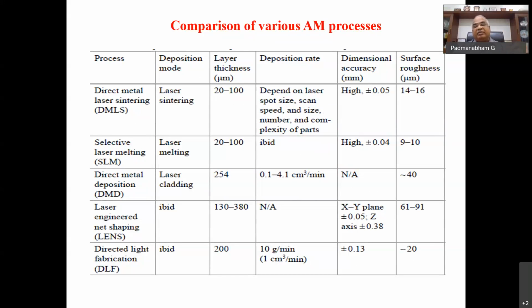This comes from the particle size that you use. If you use very fine particles in direct energy deposition, there's a problem of choking of the nozzles. That's the reason we can't use very fine powders. Because of the layer thickness, automatically your deposition rates will be different. Your dimensional accuracy will be different, and the surface roughness that you can achieve also will be different. To just give you an idea why the change in technique can cause what kind of changes in the part that you end up with.